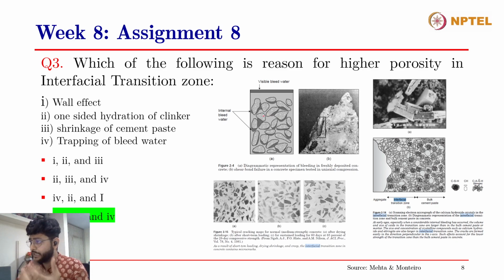When you have bleeding in concrete, the concrete essentially has a very low shear strength, and the water or the paste portion is segregating from the aggregates. So the aggregates are trying to settle down, and the cement paste doesn't have the strength to keep those aggregates in suspension. So the aggregates are settling down, and the water or the cement paste is rising on the top and accumulating as the bleed water. So this is bleeding. When bleeding occurs in concrete and there are large aggregates, this bleed water sometimes also gets trapped around the surface of these aggregates, as you can see over here. These darker portions shown in the view graph are internal bleed water.